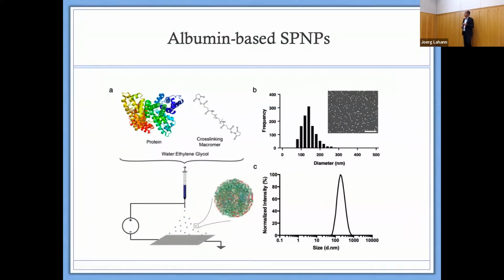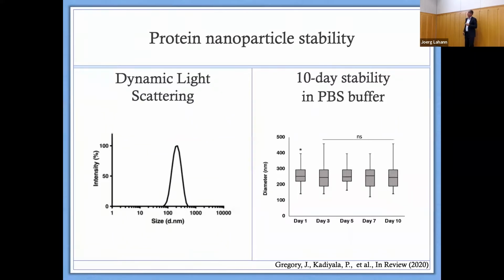And so you can see, for instance, that the particles are well distributed, about 100, 150 nanometer in size. The size distribution, even in an aqueous environment, is well defined. It's a little bit bigger because the protein swells. That's actually nice, because we also see a pH dependence, which allows us to come out of the endosome. If we go into the cytoplasm, we have to come out of the endosome, which has a lower pH. That's a very nice system. So those are great particles. They're stable over 10 days. So we're looking at the diameter over a long time. So they're stable, which is good. This doesn't work anymore, but that's okay.